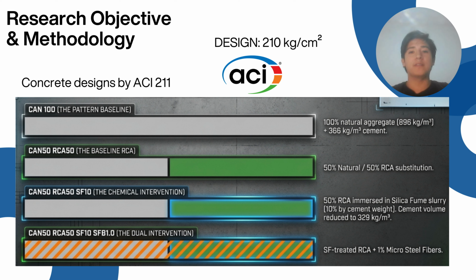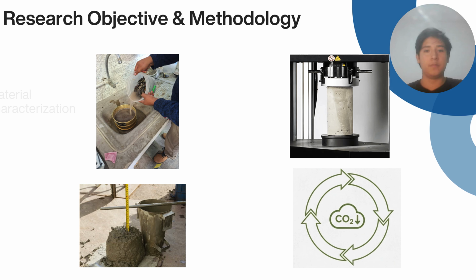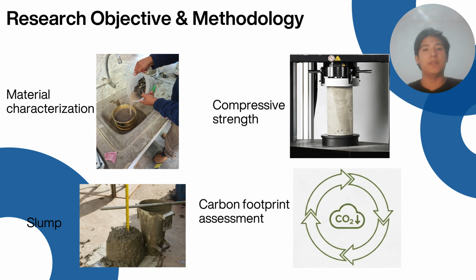Four concrete mixtures were designed according to ACI 211 recommendations. The first was conventional concrete and served as the control mixture. The second one incorporated 50% of recycled concrete aggregate. The third one included RCA treated by immersion in a silica fume slurry for 24 hours. And the fourth one combined the silica fume treatment with 1% steel fiber reinforcement. The experimental program included material characterization, slump testing, compressive strength testing at 14, 21, and 28 days, and finally a carbon footprint assessment.